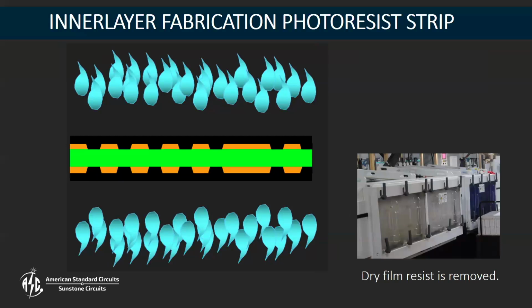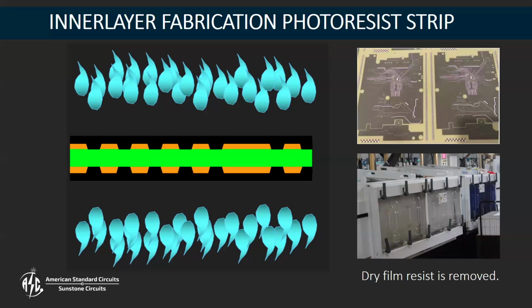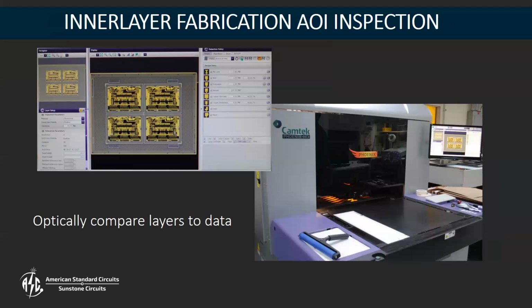All right, so the next step, we got to get rid of that photoresist. It doesn't do us any good in the manufacturing process once we've used it as an etch mask. So chemically, we run those panels through our resist stripper, and it chemically removes that photoresist now from the panel. So we're going to get basically just a panel now. Copper and laminate are the only things on that panel. So both sides get processed at the same time. Both sides get etched at the same time. The resist strip happens at the same time on both sides. So that pair goes, and it is now